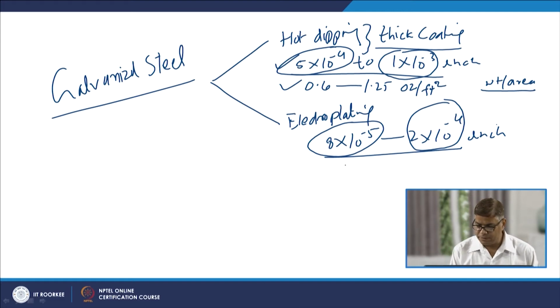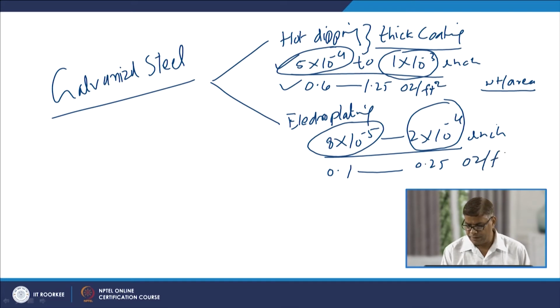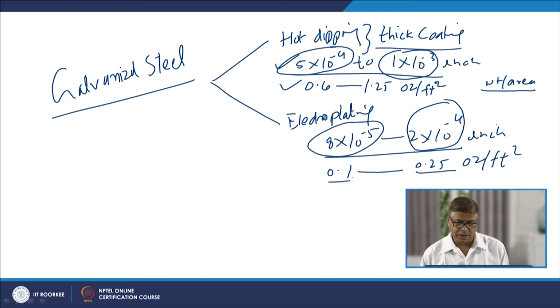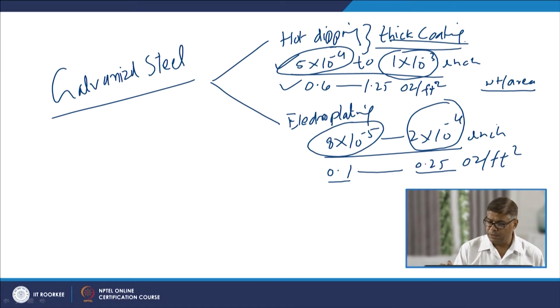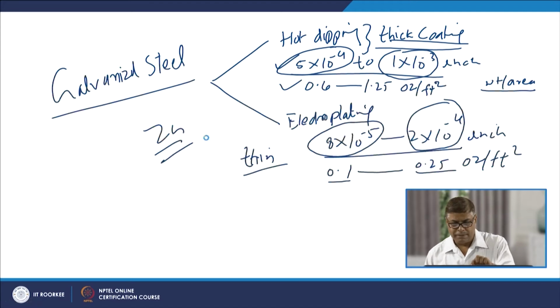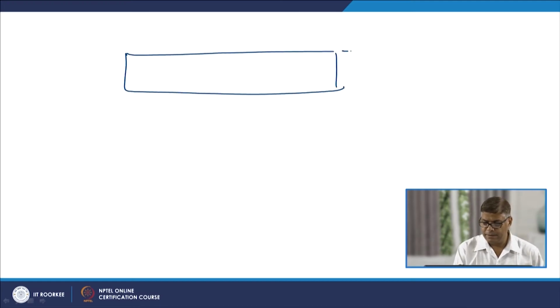At the same time, the weight of zinc per unit area in the coating, in case of electroplating, ranges from 0.1 to 0.25 ounce per square feet. So, this is significantly lower, like 4 to 5 times lower in terms of the weight per unit area of zinc in case of electroplating. So, in general, hot dipping leads to thick coatings, while electroplating leads to the development of thin coating of zinc in galvanized steels. So, the amount of zinc which will be there with the steel sheet during the welding,